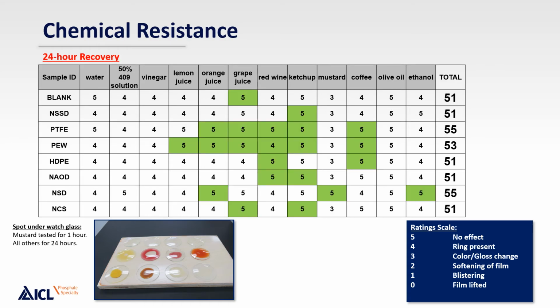The results were also reviewed after a recovery period of 24 hours. And so all of the cells that are highlighted in green showed an improvement in their rating after that time. So in this case, there are a few products that actually showed improved results versus the blank control after this recovery period, namely the NSD, which is the nanosilica dispersion, and the PTFE and the PEW. The rest of the products have the same rating as the blank, including the NSSD.